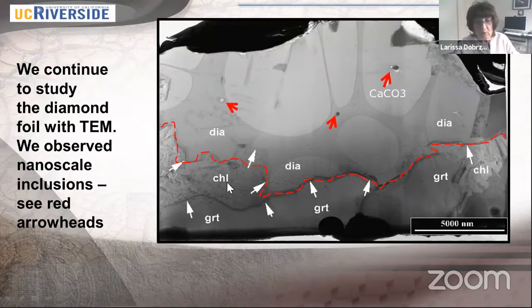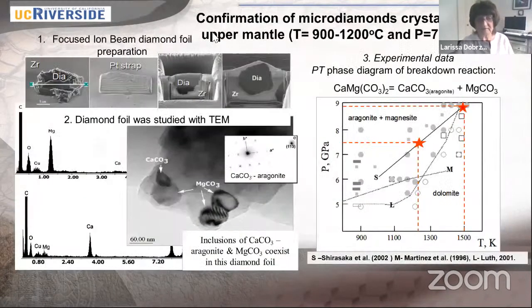Then you find here chlorite between garnet and diamond. It can be secondary chlorite. However, it was known from experiments that chlorite is stable up to 5 GPa. It can be formed in the diamond stability field as well. So again, you see chlorite between garnet and diamond. So a lot of information you can get. Now you see what we can see in this foil, what we get from that, okay? So we confirm the temperature and pressure and depth of crystallization of this diamond.